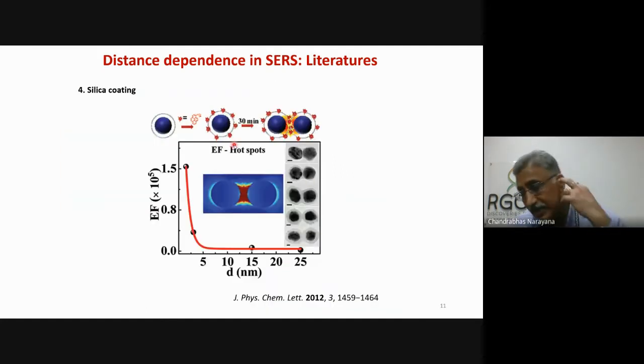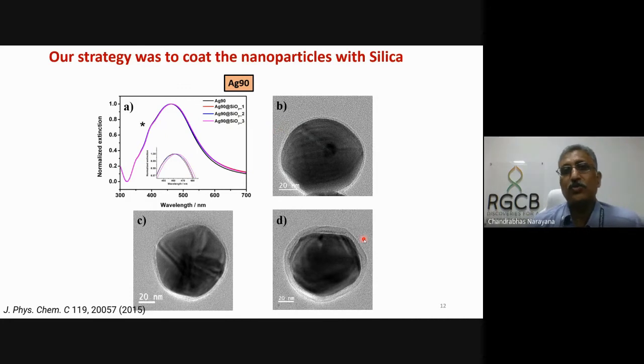And here in IISER Trivandrum, George Thomas's group tried to find out how this distance phenomenon can be studied. What they did is they coated the nanoparticle with silica of different thickness, added a dye molecule on top of it, and then did a functionalization so that the dye molecule forms a linkage. So these two dye molecules will come together to produce a hot spot in between the two systems. They found that it was very close, around 2 to 3 nanometers, the maximum detection possible. Now, again, there is a problem because this dye is also an issue when it comes to doing these things.